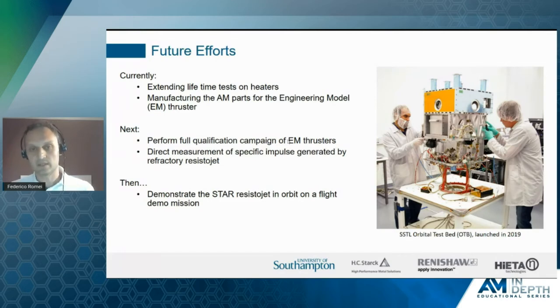And also we conduct other tests, including leak tests, pressurization tests, and probably most importantly for AM materials, we do cleanliness verification, which means that we want to see how much of the powder and in what particle size is left in the resistojet before and after the qualification campaign. This is key because there are requirements from the mission provider. So the next step at the end of this project and with this big collaboration is to launch it. So to put a resistojet into space on a demonstration mission and prove that in its own operational environment.